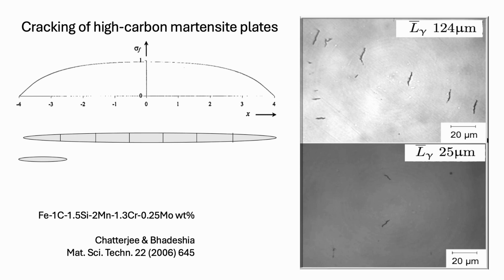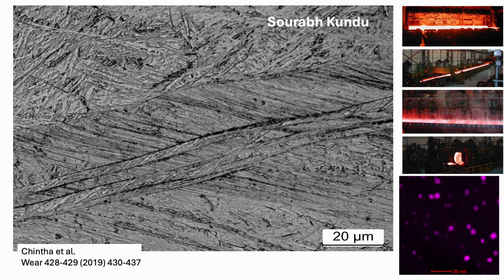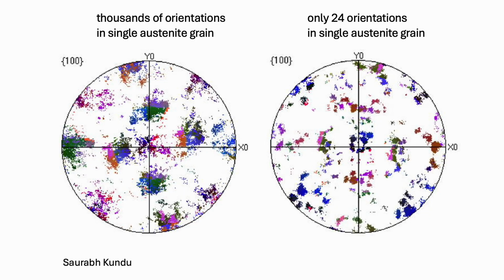Well, what we did was we took our 0.35 carbon steel and we rolled it in a proper mill at a very low temperature, something like 800 degrees centigrade. And therefore we produced a severely pancaked austenite grain structure containing lots and lots of deformation bands. So effectively it divides the coherent size of the austenite grains to a very small value. And I can illustrate that slightly differently. Here we have stereographic projections of a single austenite grain, first in the deformed austenite and second in the undeformed austenite.